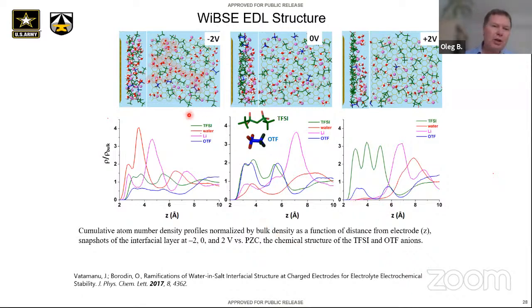However, on the negative electrode, there was bad news. Once we polarize to -2 volts, lithium, as one of the species, wants to go in, and lithium is preferentially coordinated by water. And now it's a negatively charged electrode. It doesn't like negatively charged species, which are anions, which are the majority of the electrolyte. So anions go to the second solvation shell.